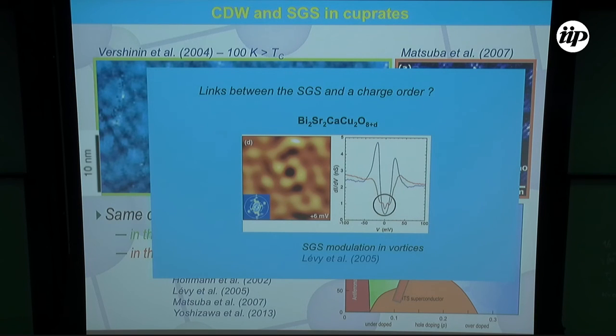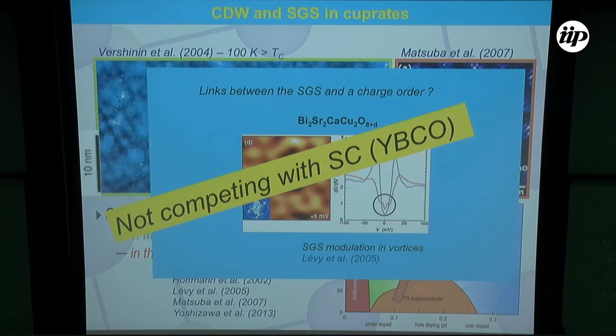So this subgap state seems to be completely linked with this modulation, which is also linked with the charge order. So it's quite tempting to associate this subgap state with this charge density wave, which is now routinely measured in the cuprates. With an important conclusion, if that happens to be true: crossing a vortex, having a field or not, is not affecting at all this signature of finite energy state, which would mean that this state, and possibly the charge density wave, is not competing and doing nothing special with superconductivity. They just coexist, as we claim with this two parallel channel model.